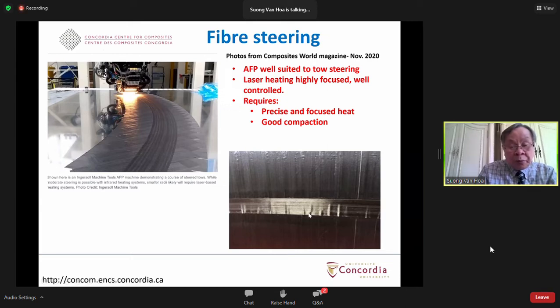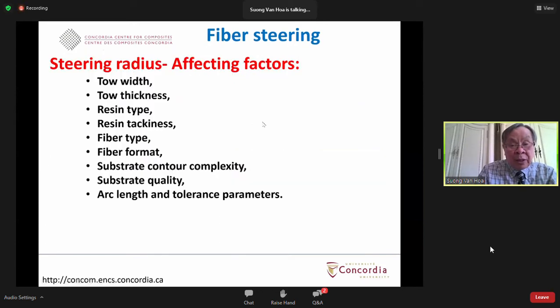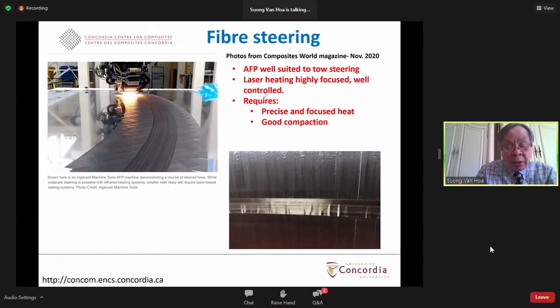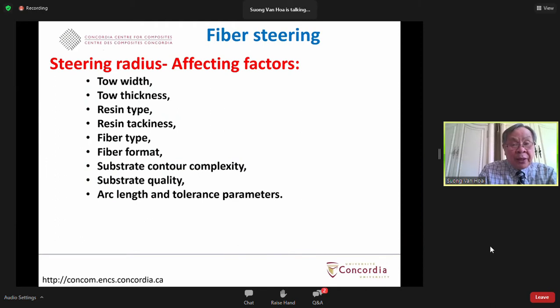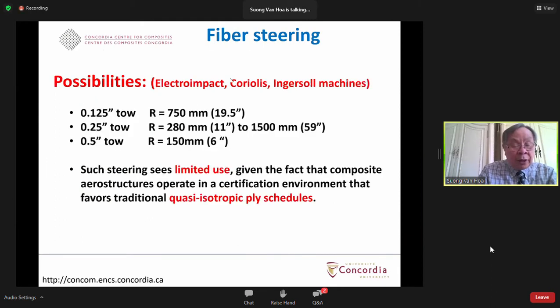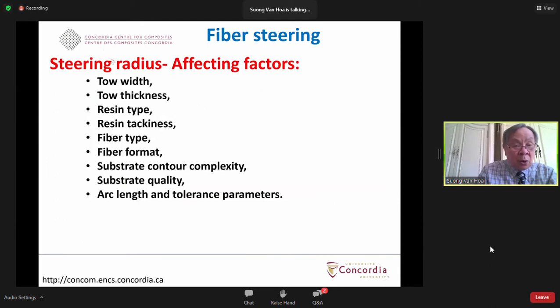In order to improve this, you need precise, focused heat and good compaction pressure to control this aspect. People found that laser heating is a better way of heating, because it has more focus and good control. There are many factors affecting the steering radius: tow width, tow thickness, resin type, resin tackiness, fiber type, fiber format, substrate contour complexity, substrate quality, arc length, and tolerance parameters.